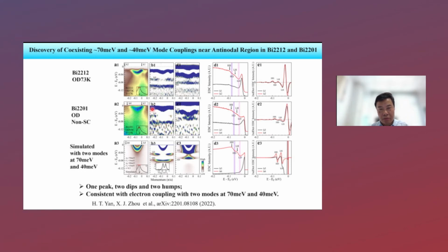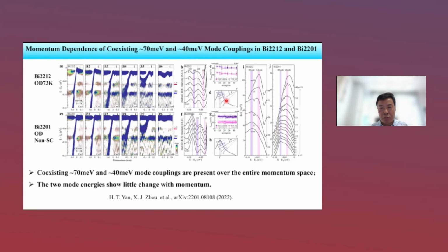They are always together. Then, if we do the momentum dependence, we go from the nodal direction gradually to the antinodal direction. You can see that these two mode couplings, 40 millivolt and 70 millivolt, are always present along all the momentum cuts from nodal direction to antinodal direction in both Bi2212 and Bi2201. Okay, and also you can see that the mode energy does not change much with the momentum change. So basically, they are constant when we move from the nodal direction to antinodal direction. It's a very small change here.